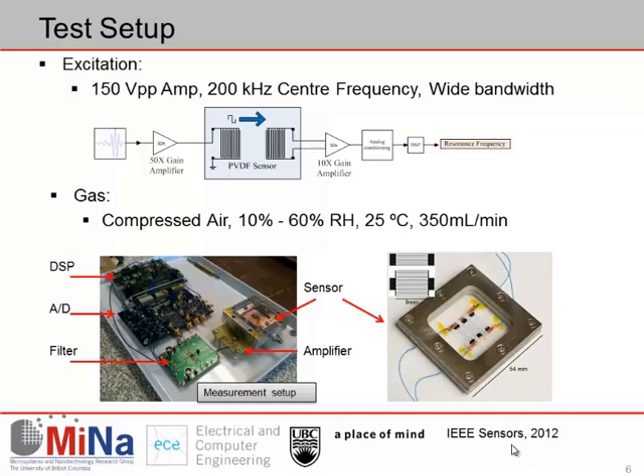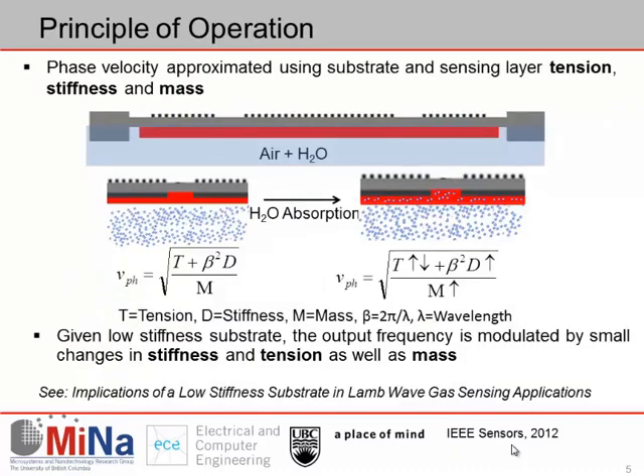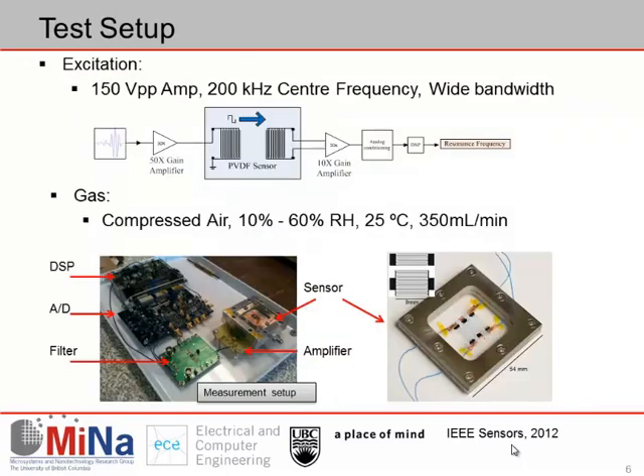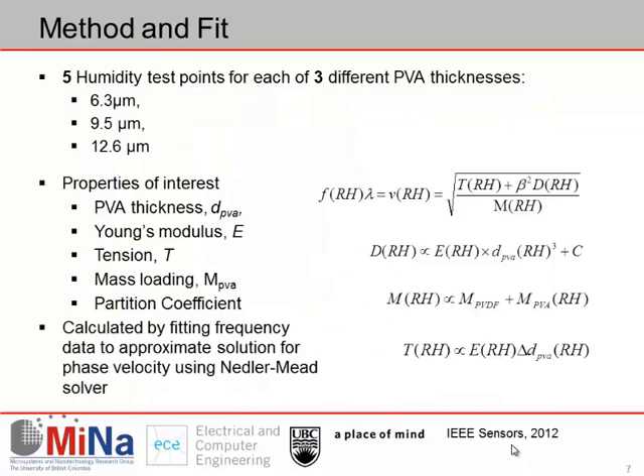I forgot to mention on the previous slide, what we're looking for is specifically how tension, stiffness, and mass change as a function of relative humidity when we expose PVA to increasing amounts of water. As we increased the RH, we measured the shift in frequency, and we're able to detect how tension and stiffness changed. A better description of how we did that is given here. We had one sensor to which we applied three different thicknesses of PVA, 6.3, 9.5, and 12.6 microns. And for each of these three thicknesses, we exposed the sensor to varying levels of relative humidity.